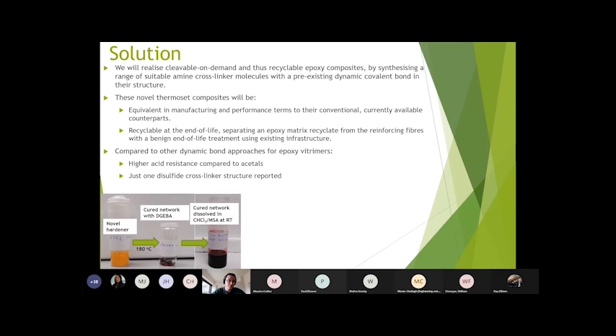Now, the idea of incorporating a labile bond in the network to produce epoxy vitrimers is not a new one. It has been tried by other people, and there are a couple of very well-known examples. We have the acetals, also known as recyclamines, that have been commercialized by Connora Technologies, which are already out there, and there is a large variety of them, but to our knowledge, acetals have an issue with acid resistance. They basically can be hydrolyzed in the presence of trace acid or even moisture. So that would be an issue with respect to the actual operation of the material.